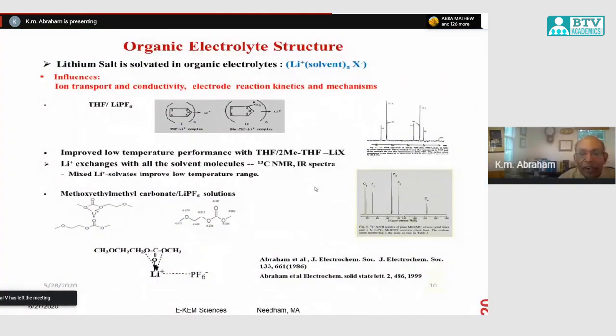I did some work early on to understand the structure of organic electrolytes. I used NMR, nuclear magnetic resonance experiments, to show that the lithium ions are solvated. That means in this case, with tetrahydrofuran and 2-methyl tetrahydrofuran, they form complexes with the lithium cations. And so you have solvent-separated ion pairs here where the lithium is solvated.